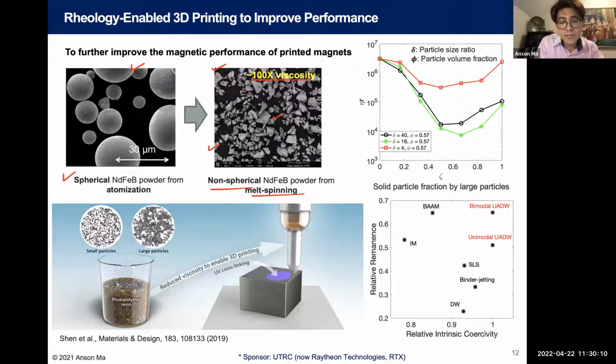So it goes back to some work done in the 70s, a long time ago, when people looked at suspension rheology. One thing they realized is that it's not just the volume fraction of particles you put in there, but the particle size distribution also matters. If you have a bimodal particle system, you have big particles and small particles. By manipulating the particle size ratio between the big and the small particles, and also how many big particles relative to the small particles, you can actually find a sweet spot.